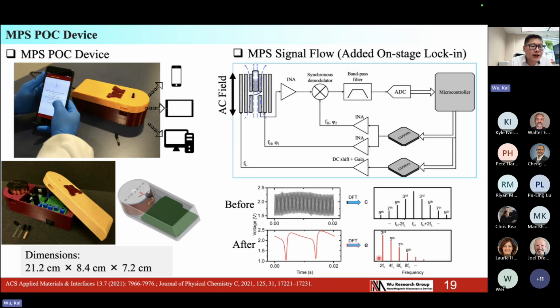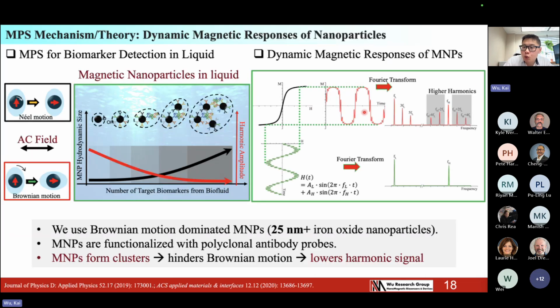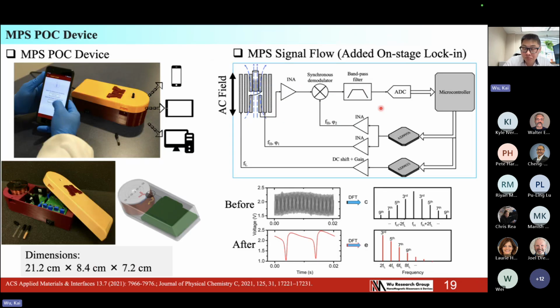Here is a photograph of the POC device we developed in 2021. As you can see, on the circuit board we have the microcontroller to control the generation of the sinusoidal waves, one with the high frequency FH, one with the low frequency FL. These high and low frequency sinusoidal waves drive the coils to generate the AC magnetic field. This field is applied to the nanoparticles, which we put in the glass vial in the center. The nanoparticle signal is collected by a gradiometer. This gradiometer converts the time domain magnetic signal to a voltage in the coil following Faraday's law. After we get the voltage from this pickup coil, we do amplification, filtering, and ADC conversion to get the frequency domain of the signal, the harmonic amplitude.